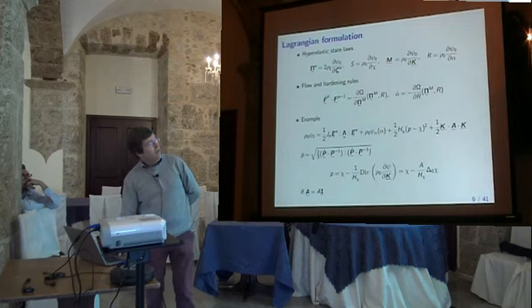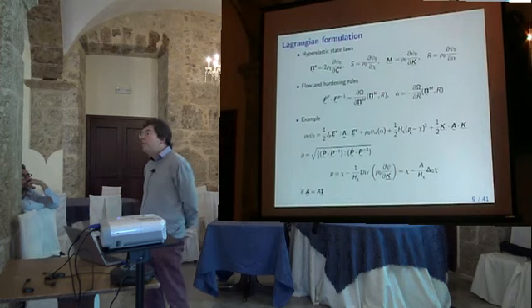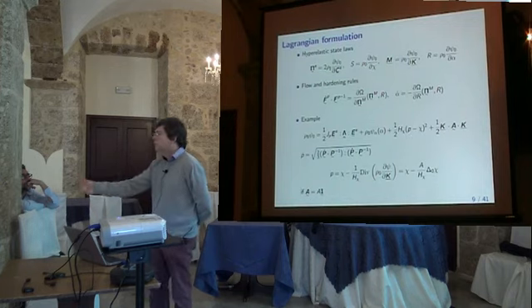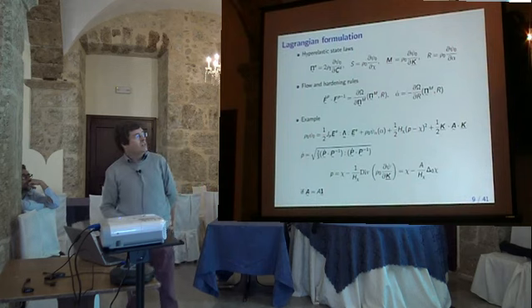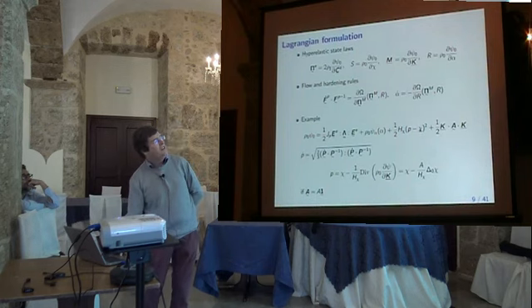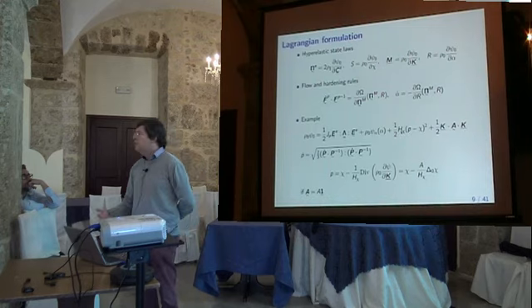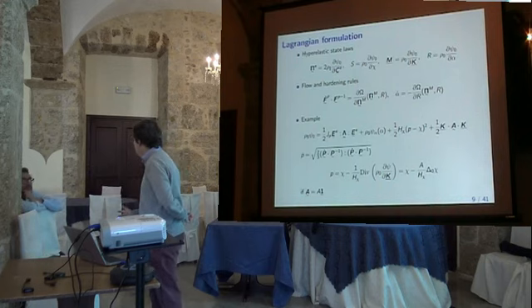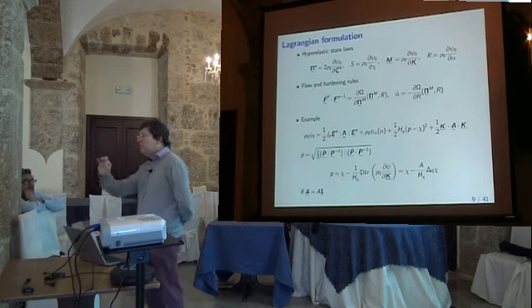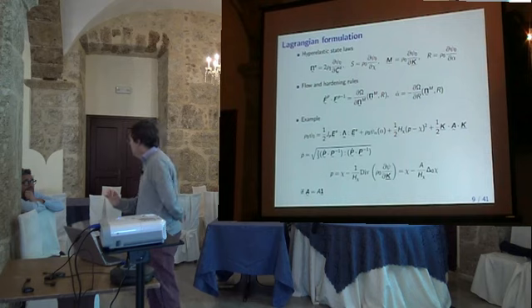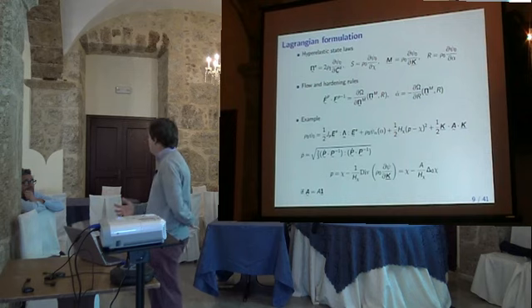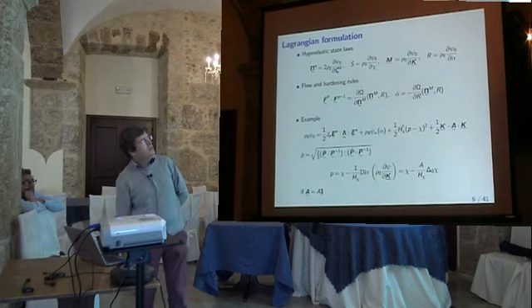What is it? It is close to the plastic strain. This one is simply the cumulative plastic strain that you have in the plastic flow rule for isotropic materials. And you see that I penalize the difference between this quantity by a quadratic potential and the modulus here, which you can consider as a constitutive modulus, or if you don't really like it when you don't understand physically what it is, you can say this is a penalty term. You penalize the difference between the micro and macroplastic deformation.